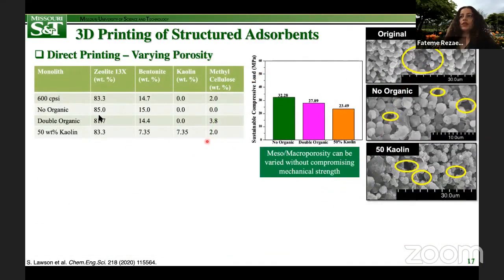In conjunction with the previous slide I discussed a few seconds ago, this slide shows how porosity can be tuned through printing as well. In other words, we're also able to vary porosity for 3D printed structures using a direct printing approach. This could be achieved by varying the printing paste composition, either by removing or doubling the organic additive, or by adding a microporous binder such as kaolin.